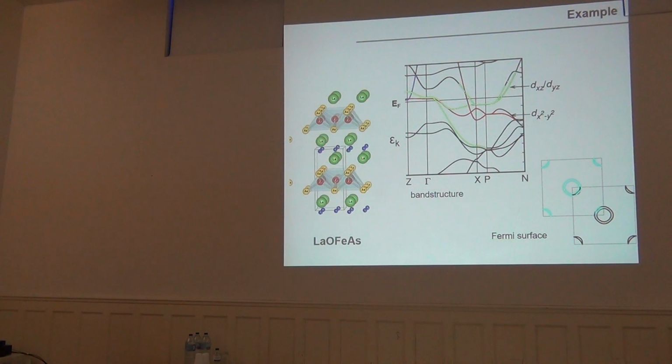This kind of effect can be thought of in this way. You have these very special vectors where the electron doesn't need any energy to go from the electron to the hole pocket, and therefore the system will use its internal mechanisms to pin itself into a lower energy state, which in this case will be the pi or the pi zero, depending on which unit cell you're talking about, which will be the stripe order that the system forms. This is what it means.